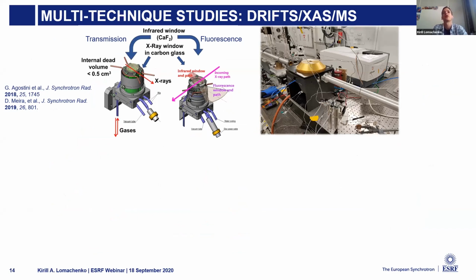So in particular, at BM23 beamline at ESRF, we have a combined XAS-DRIFTS setup coupled also with mass spectrometry, which allows you to get mass spectra, XAS spectra, and infrared spectra from the same sample at the same time, at controlled temperature and controlled gas composition.